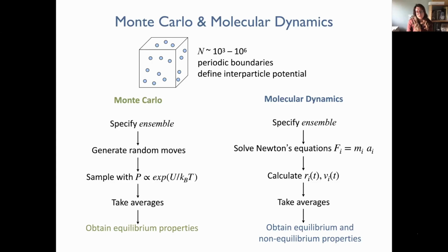Monte Carlo is very good for obtaining equilibrium properties. Molecular dynamics gives the same, but we can also get non-equilibrium properties since we can track how the system moves towards equilibrium. In all cases, we used periodic boundary conditions and boxes containing a lot of particles, like 10^3 or 10^6, depending on the system.